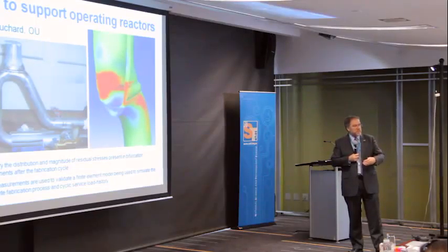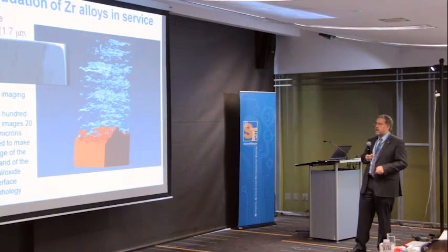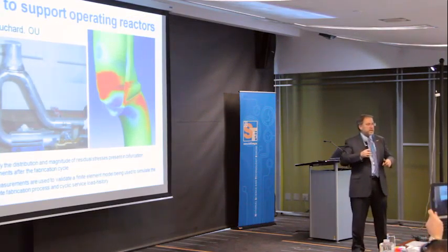So there's a mock-up of the bifurcation. So that's the weld material. You can look at the neutron diffraction. It tells you what the stress distributions are. You can then do certain heat treatments to remove that type of distribution of residual stress, and you can use modelling, finite element modelling then, to make those sorts of predictions.